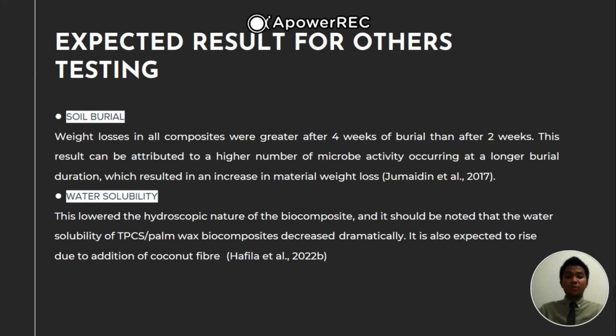For soil burial, weight loss in all composites was greater after 4 weeks of burial than after 2 weeks. This result can be attributed to a higher amount of microbial activity occurring at a longer burial duration, which results in an increase in material weight loss. Lastly, water solubility. This lowers the hygroscopic nature of the biocomposite, and it should be noted that the water solubility of the TPCS plus palm wax biocomposite decreased dramatically. It is also expected to rise due to the addition of coconut fibers.